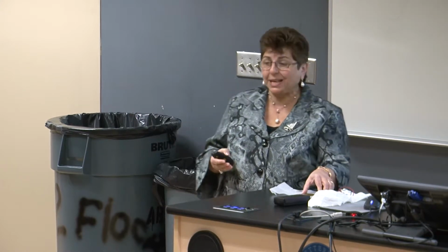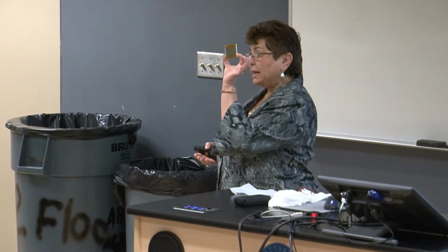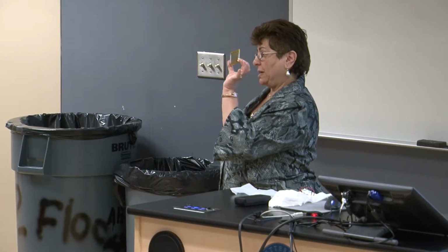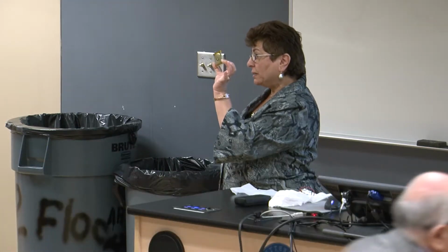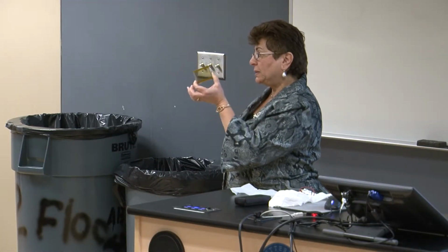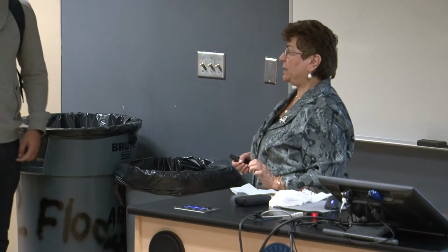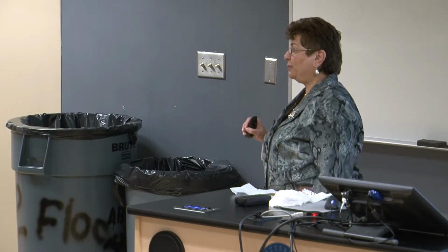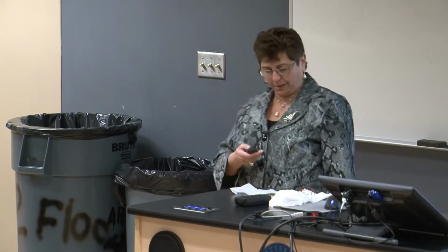Those are the materials. Generally, in a device structure, you always use two of them as complementary. If one of them is a cathodic material, the complementary layer should be an anodic material. So this device has two electrochromic layers. One is a cathodic material, which is tungsten oxide. The other one is an anodic material. I am not going to tell you, but it's a composite material.